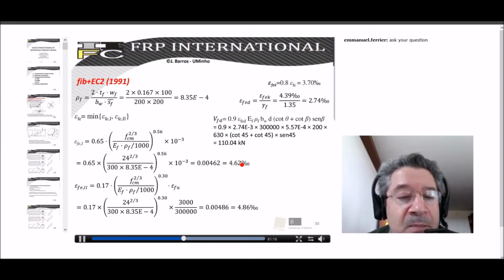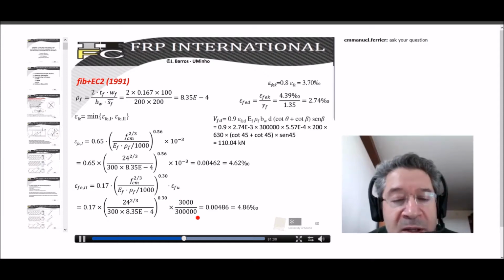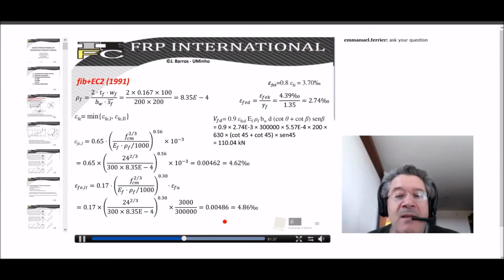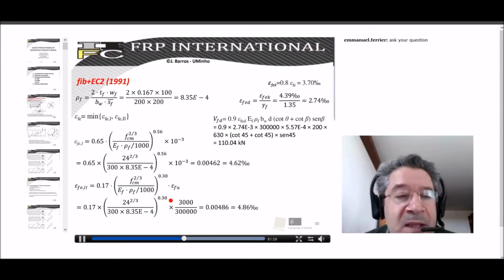For the other equation, we obtain a quite similar result, but it is based on, or you should also consider, the ultimate strain of the FRP, and we obtain about 4.9. So this means that the effective strain should be considered 4.62 per mille.